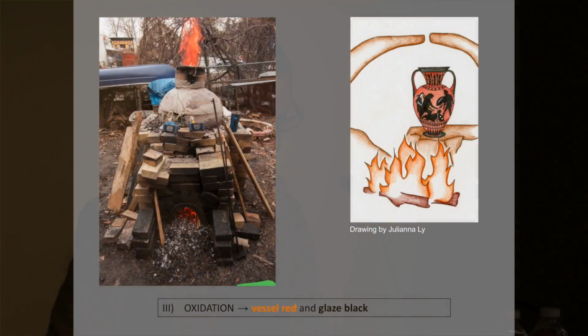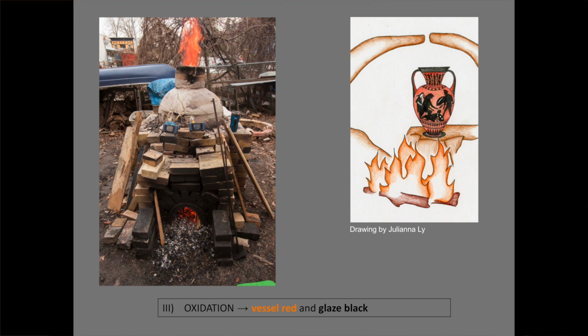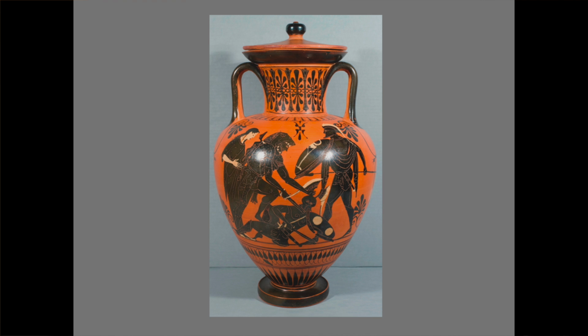In the third phase, the reoxidation phase, the kiln was cooled somewhat and the vents were opened again, allowing oxygen to re-enter the kiln. The oxygen turned the black parts of the vase body red again, but the painted parts remained black because the oxygen could not reach the iron oxide molecules within the painted portions, because they were now trapped within the glassy matrix. Once the kiln had cooled, the finished vase was removed, and it now displayed the design in the black and red colors.